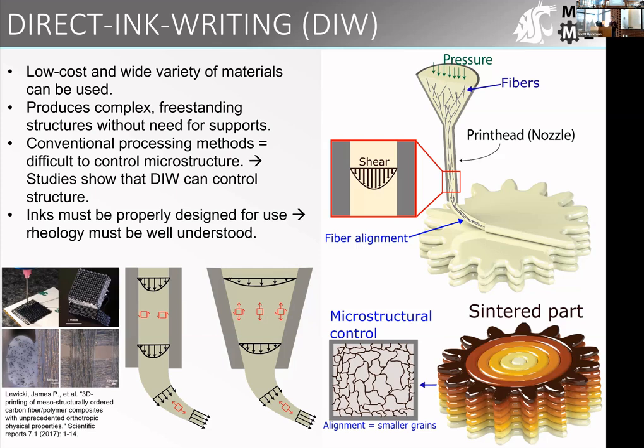And so basically, because of the way this method works, as long as your material can flow, you can use it in direct ink writing. And that means that you can use a wide variety of materials. So you can have these liquid materials loaded with whatever type of particle you want. And interestingly, studies have shown that the flow mechanisms that these materials are subjected to during this process lead to particle alignment, meaning that not only can you create complex geometries with this method, but you can create unique microstructures that are not possible with the conventional processes that I talked about before.